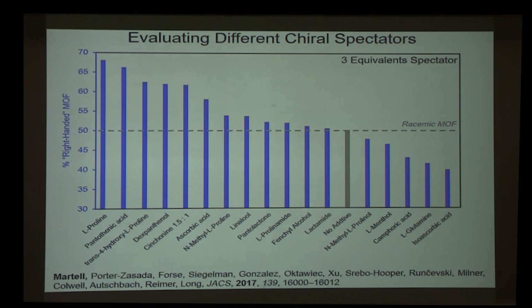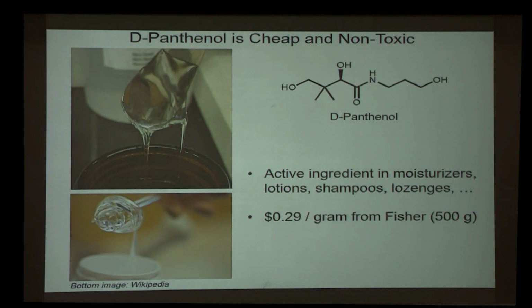So for further optimization, we selected this chiral spectator. And the reason we picked this one is in data I don't have time to show you, I found that this spectator produced the highest quality MOF in terms of crystallinity and porosity. This is the compound called panthenol that I used for further optimization. It is a chiral alcohol that is an active ingredient in moisturizers, lotions, and shampoos. So it's industrially produced, it's non-toxic, and it's quite cheap, which is important because if we were to use this in the synthesis of a chiral material, it would not greatly increase the cost.